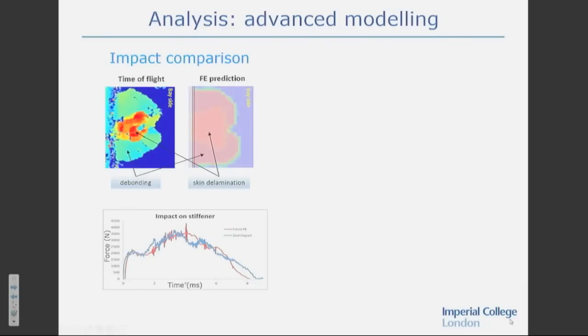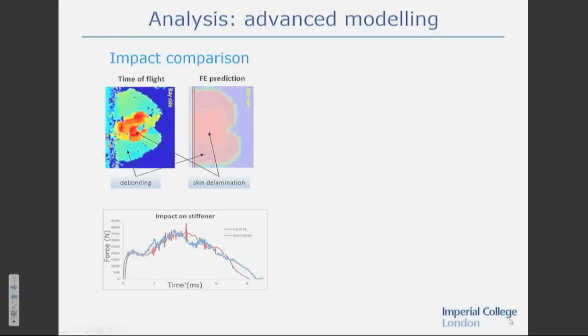If we now do the comparison between the finite element modeling and the experiments, first of all, just for the impact, this is the damage detected by the ultrasound technique, and this is the one predicted by our numerical model, so we've got good agreement there. And then if you look at the force time response during the impact, the blue one is the experimental result, the red one is our numerical prediction, so good agreement there.